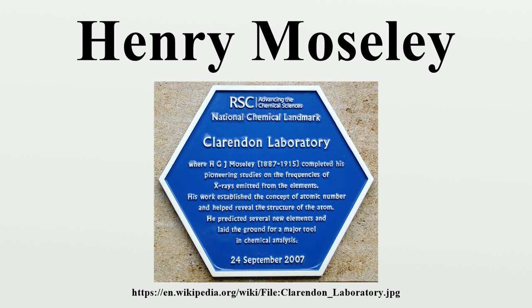X-ray spectrometers are the foundation stones of X-ray crystallography. The X-ray spectrometers as Moseley knew them worked as follows: a glass bulb electron tube was used. Inside the evacuated tube, electrons were fired at a metallic substance, causing the ionization of electrons from the inner electron shells of the element. The rebound of electrons into these holes in the inner shells then causes the emission of X-ray photons that were led out of the tube in a semi-beam through an opening in the external X-ray shielding. These are next diffracted by a standardized salt crystal, with angular results read out as photographic lines by the exposure of an X-ray film fixed to the outside of the vacuum tube at a known distance. Application of Bragg's law then allowed the wavelength of the emitted rays to be calculated.